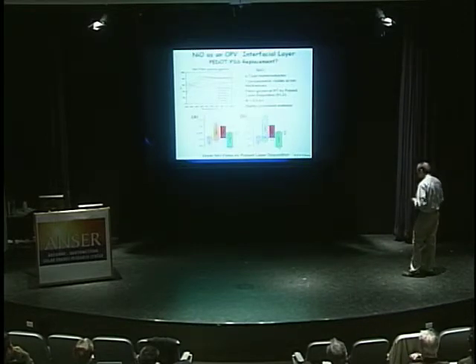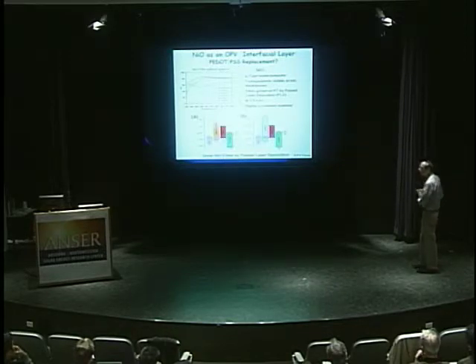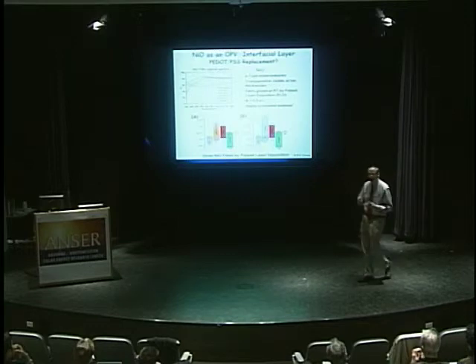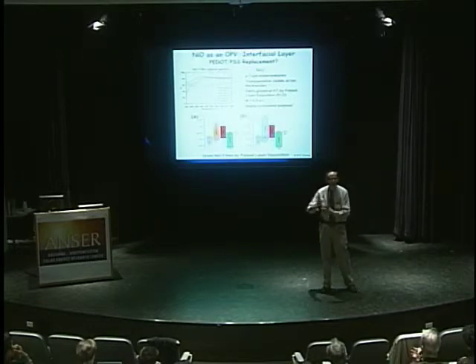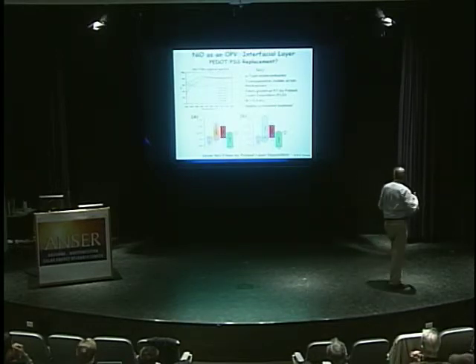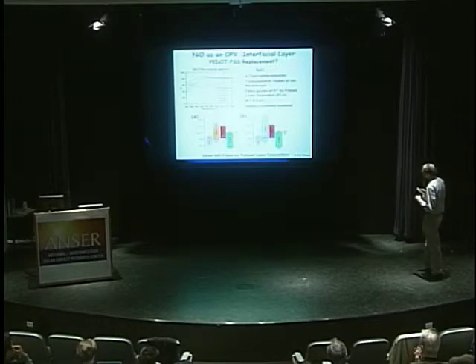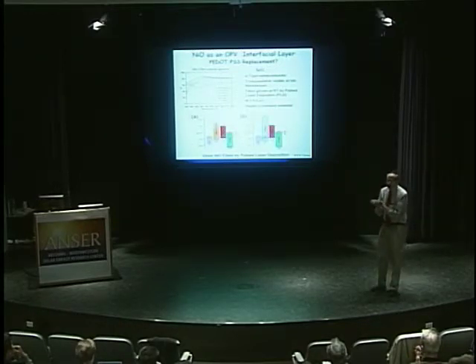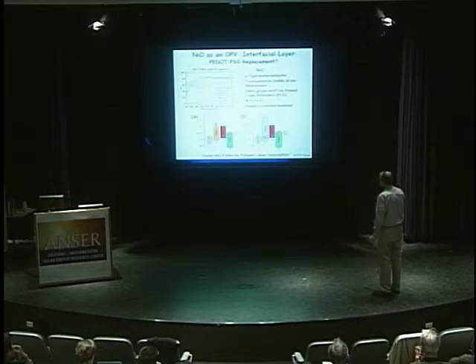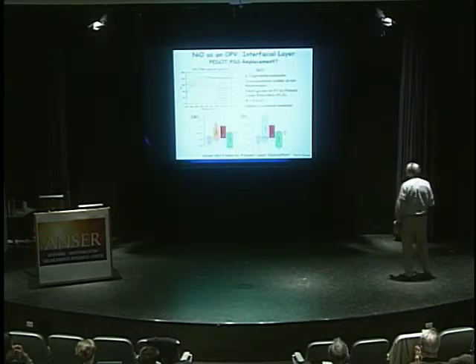We grow the films, we meaning Bob Chang, my colleague in material science, grows the films by pulsed laser deposition. It's a very good exploratory growth technique for growing a film of anything on anything. I think that's a fair statement. In terms of nickel oxide, it's got a rock salt structure. I would say you can easily find 20 papers in Physical Review B, all 20 pages long, on its electronic structure, because it's a highly correlated material.